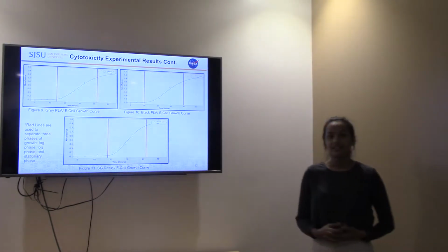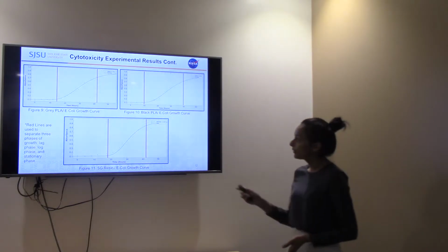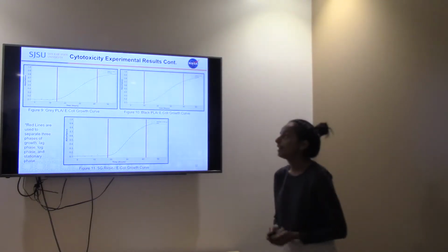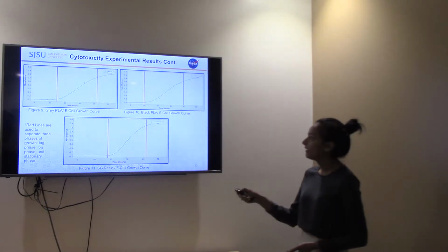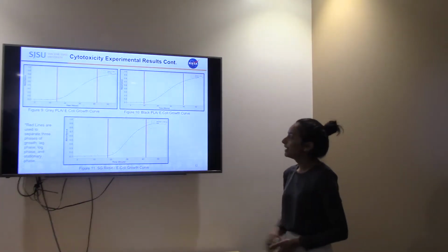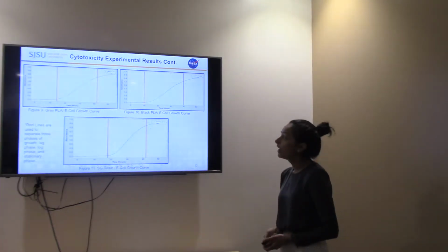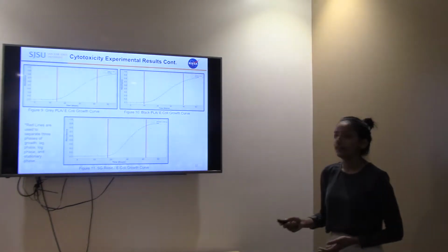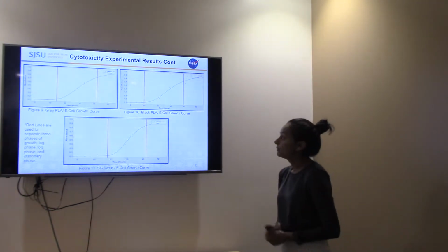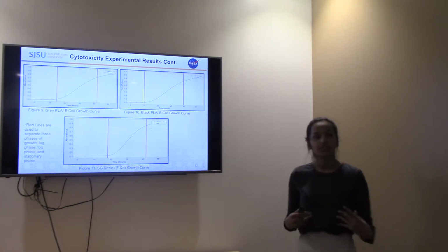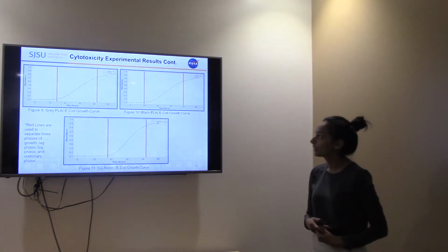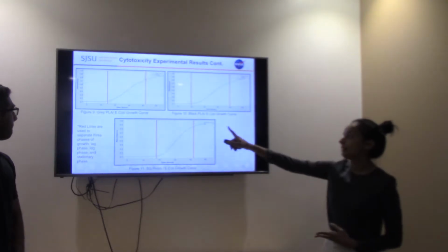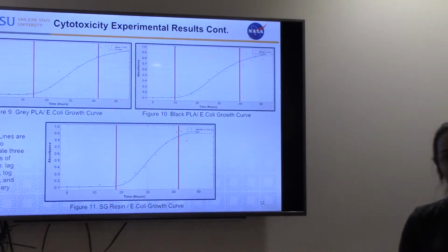Using the absorbance and time, we plotted a growth curve on MATLAB, which we analyzed into 3 different phases. We have the lag phase on the left side, the log in the middle, and the stationary phase on the right. What we saw was none of the materials were cytotoxic. The curves resembled a typical E. coli growth curve. However, the main change was in the initial lag phase, which was the time it took for it to start reaching its growth period.